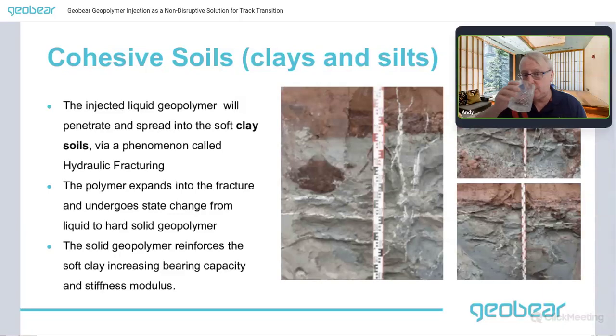So how does geopolymer work? The picture here shows a cross-section through an excavation in clay where geopolymer has been injected. You see that the geopolymer here is forming what look like lines or planes of white material against a grey or brown background. Those are actually fractures in the soil that have been filled in with hard geopolymer. The injected liquid geopolymer will penetrate and spread into a soft clay via a phenomenon called hydraulic fracturing. The polymer extends into the fracture and undergoes a state change from liquid to hard solid geopolymer. The solid geopolymer reinforces the soft clay and increases the bearing capacity and the stiffness modulus, on a volumetric ratio of polymer to clay. The more geopolymer you put in, the more strength you get, almost directly proportional. That's how you reinforce cohesive or soft clay materials.